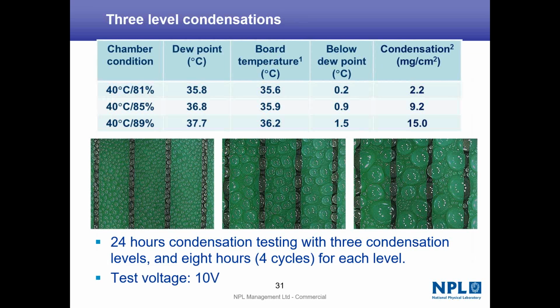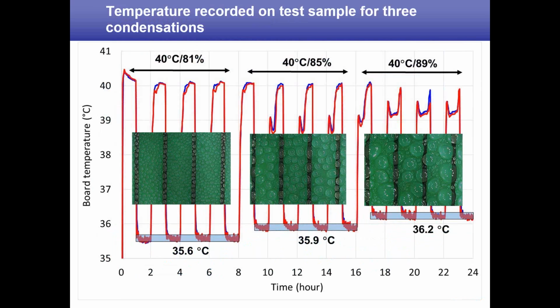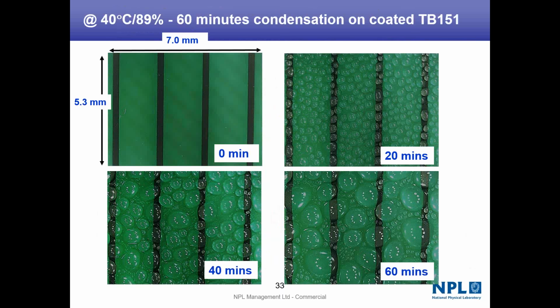So to be able to control this gives you a more defined and more controlled method of increasing the potential for failures. So what I'm showing you here is again just a graph which shows the relationship of temperature, both dwell and change in temperature, and the effect of condensation on the surface of the printed circuit board. And here we've got a close-up view of 0, 20 minutes, 40 minutes, 60 minutes. But by changing the temperatures of the environment this board sees, we can actually control the amount and how quickly this forms, or the moisture forms, on the surface of the printed circuit board.